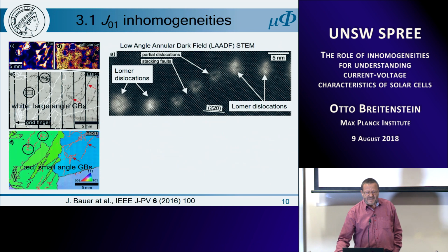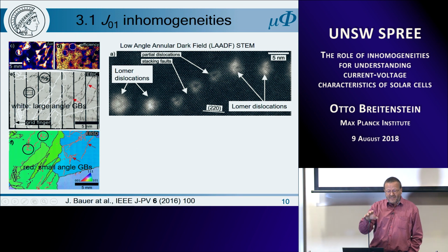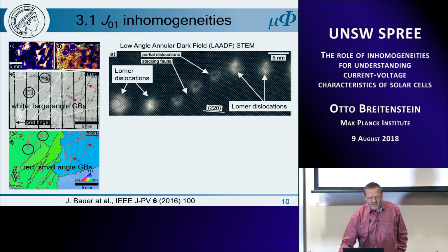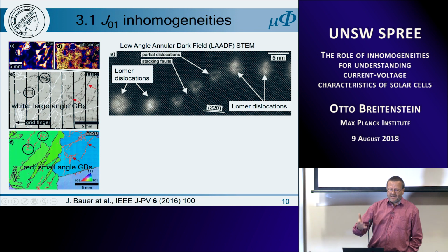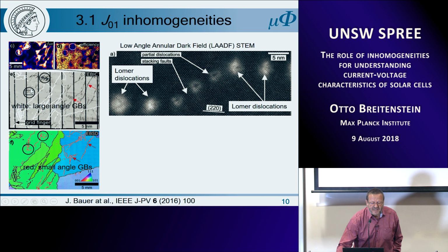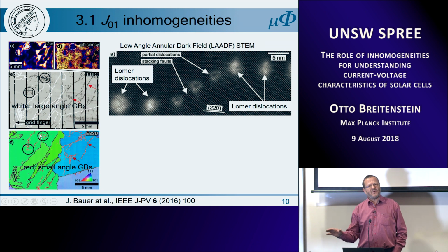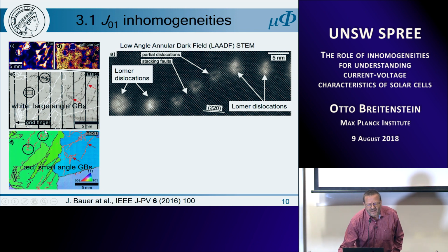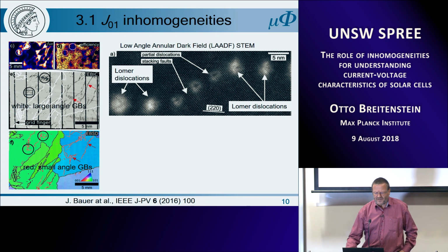So what we have done. At the left, we see this lock-in thermography based diffusion current. The diffusion current is the first diode current in this two-diode model, which is due to the bulk lifetime mostly. And in the defect regions, it shows a maximum. And for these two maximum regions, here is the corresponding EBIC image of this region. Here we see these dark lines, and these dark lines are small angle grain boundaries. This is visible here in the orientation, and we see in all these regions we have basically the same orientation, and these red lines are small angle grain boundaries, which have an inclination of only a few degrees.